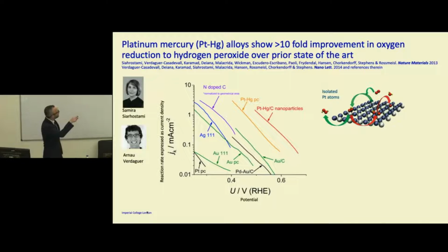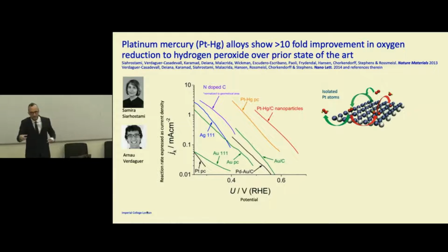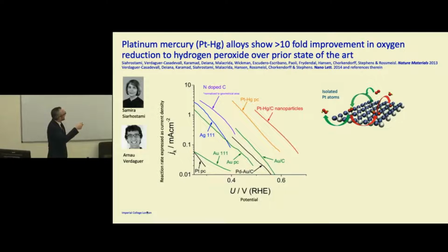And I think what's really important to maintain this oxygen-oxygen bond is not to have two contiguous platinum atoms. You need two contiguous platinum atoms to actually break the oxygen-oxygen bond. So if you have isolated atoms, you can end up making hydrogen peroxide. So we tested it, and this is the current reaction rate as a function of potential. So ideally, you want to be up here. We're very close to ideal. So we're very excited about this result.